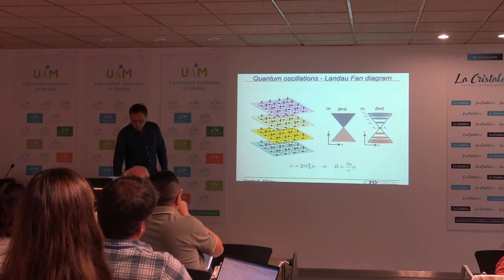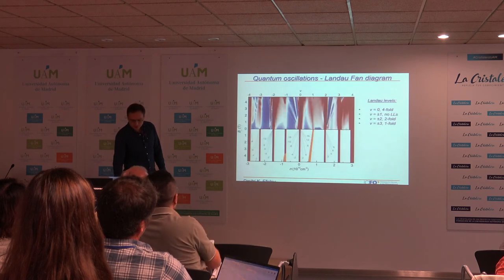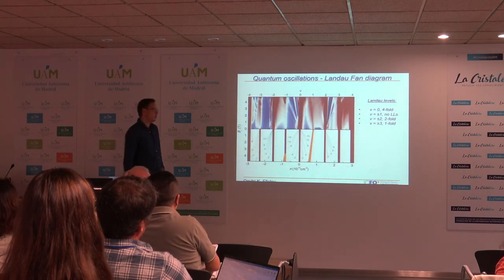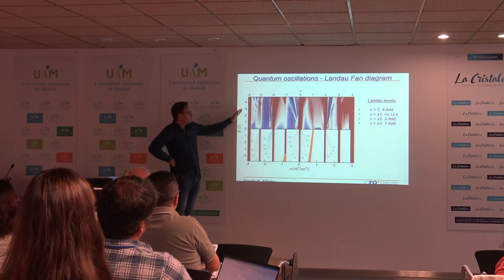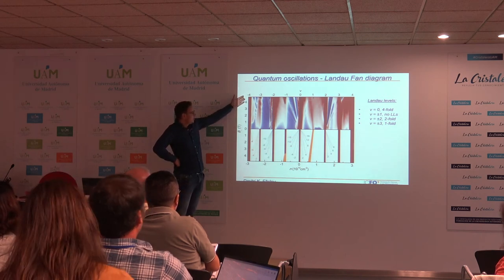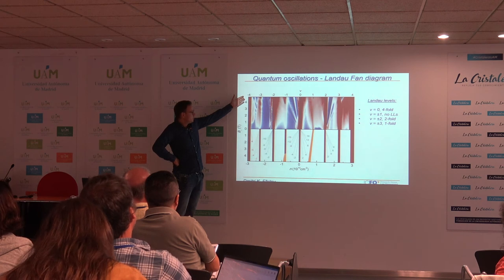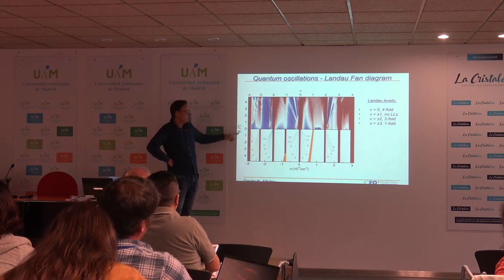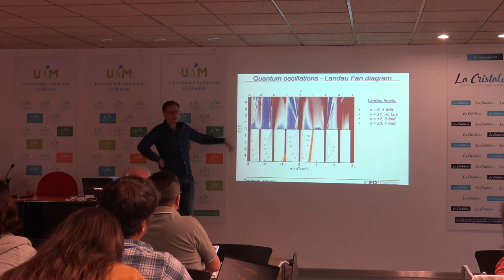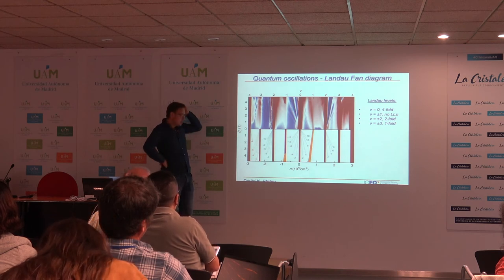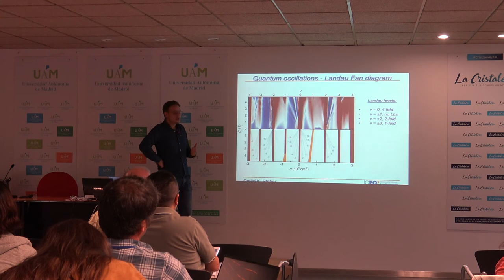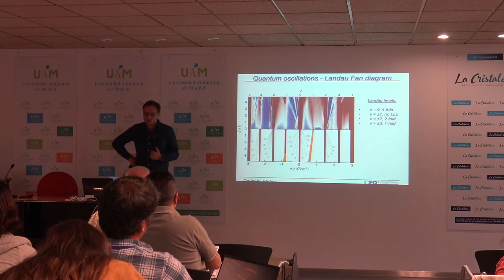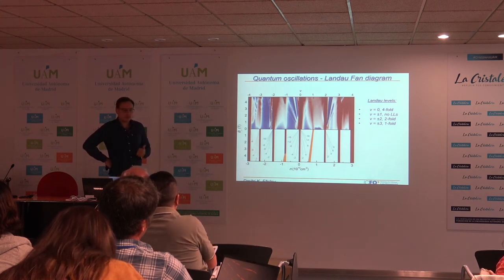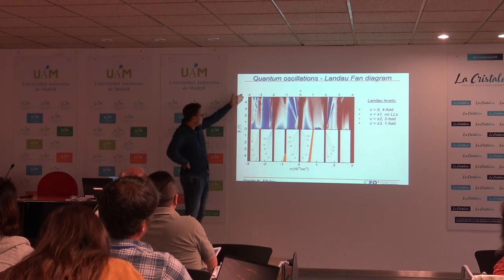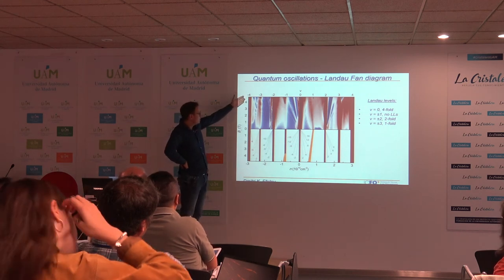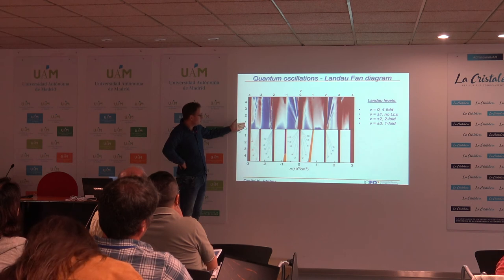And this is happening in these Landau fan diagrams, which we can measure. So in a typical Landau fan diagram like this, we're applying a perpendicular magnetic field to the system. We create Landau levels in the underlying bands, and now we can look in more detail at these Landau levels and try to understand the degeneracies. Again, this is just a resistance measurement as a function of perpendicular magnetic field.